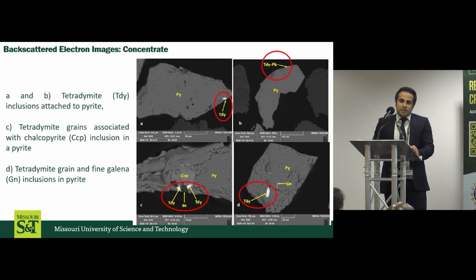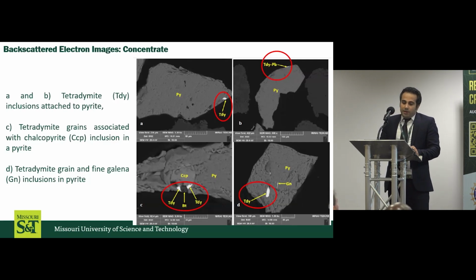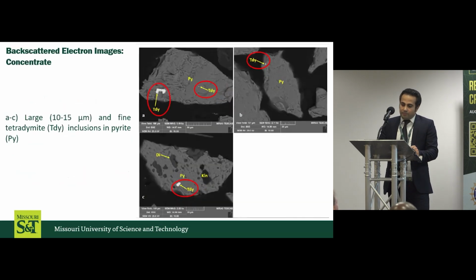In the following slides, I'm going to show you very interesting backscattered images of the concentrate. In this slide, you can see tetradymite inclusions attached to pyrite, and tetradymite grains associated with chalcopyrite inclusion in pyrite, and a large tetradymite grain and fine galena inside the pyrite. We found large and fine tetradymite inclusions in pyrite.